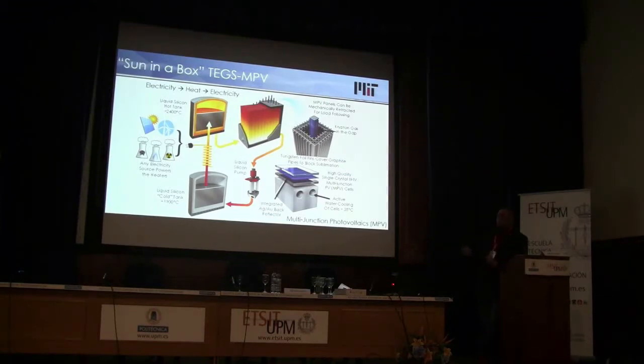But we're trying to push the temperature as high as possible because we're trying to push the spectrum as far to the higher frequencies as possible, because we're going to do the conversion with PV rather than a turbine. We only need roughly a 500 degrees C delta T in order to be cost effective, and we could actually go lower than 1900 degrees C. The liquid won't freeze until about 1500 or so. So we have more room to play, but this is our nominal operating condition that we envision.